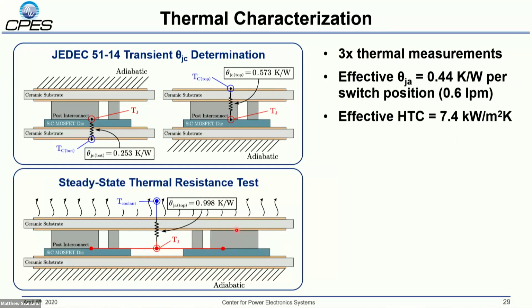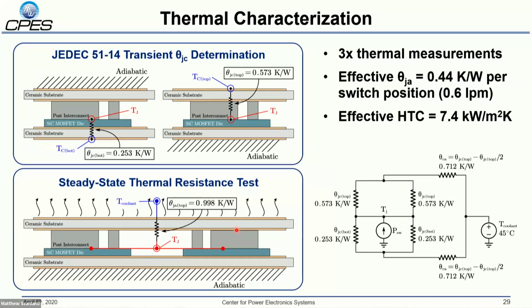So once I have these 3 measurements, I can combine them into an equivalent thermal resistance network to understand the complete system. And what we found is that we have an effective junction to ambient thermal resistance per switch position of about 0.44 K per watt. And that's at a fairly conservative 0.6 liter per minute flow rate.